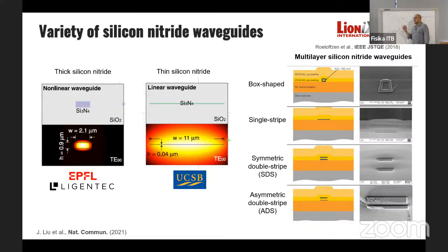But then as you go higher and higher, you have cracks occurring in the layer, right? Of course, if you have cracks, then you cannot use a lot of the area of your wafer. And why is that? This is because there is a strong difference between the stress and strain between the silicon oxide layer and the silicon nitride. So you have some shrinkage in the material that creates these cracks, right? Starting from my explanation that I need thickness for dispersion engineering, good nonlinear optics, and good confinement, this presents a problem, because the thickest that I can do is 300 nanometers.